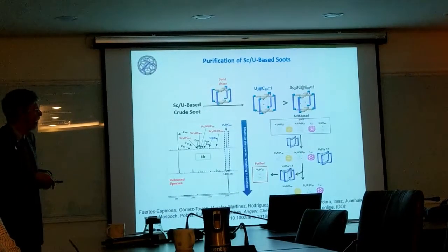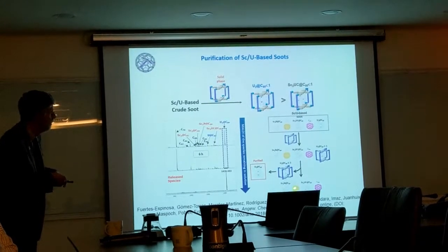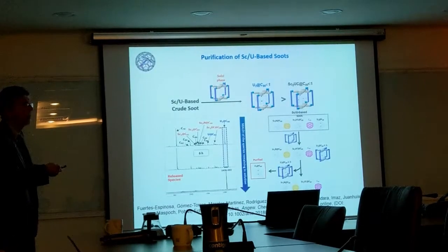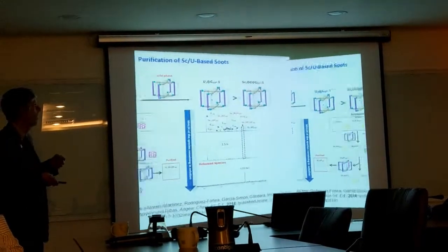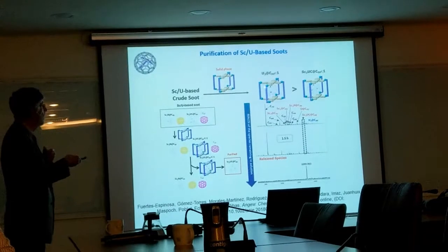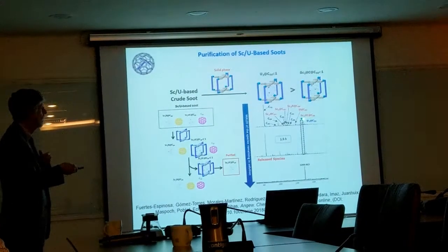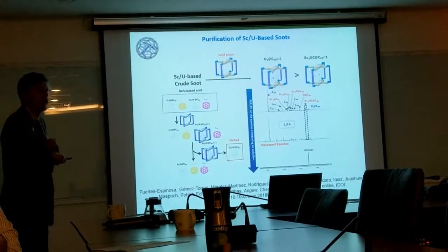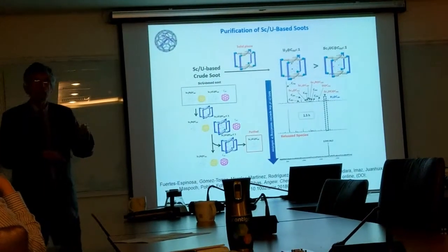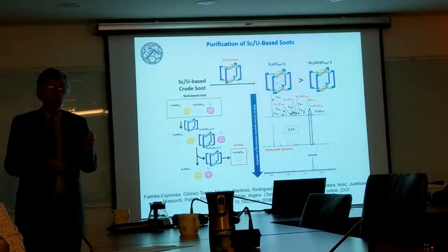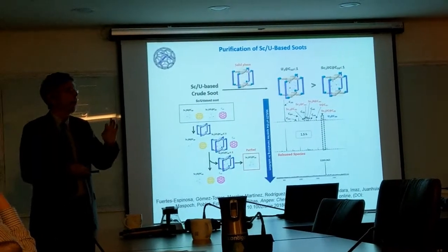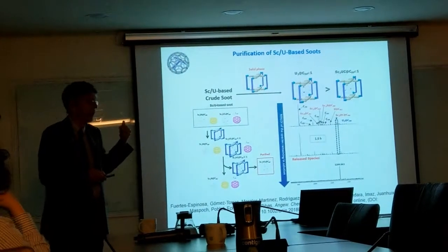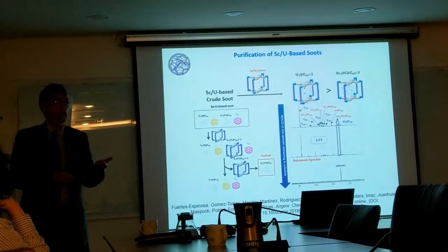And it turns out, if you keep adding to the remaining solution, the solution where you have eliminated this one but have everything else remaining, you keep adding more solid capsule. What you see is the selective complexation of scandium-2 uranium carbide until it disappears, and then you can release it as well. So we have purified 2 compounds sequentially without HPLC at all, which is absolutely fantastic. We're really very excited and looking forward to further purifications.